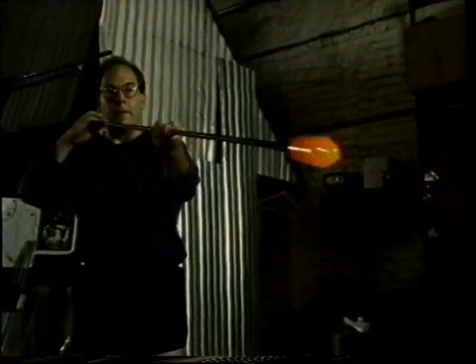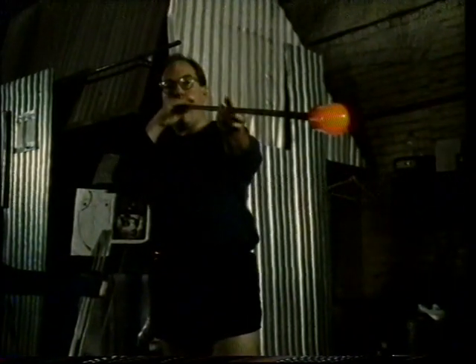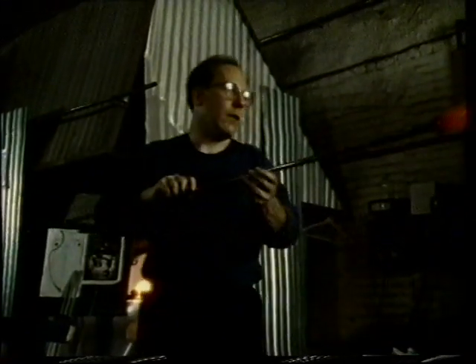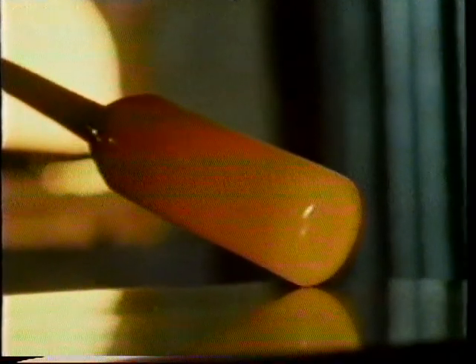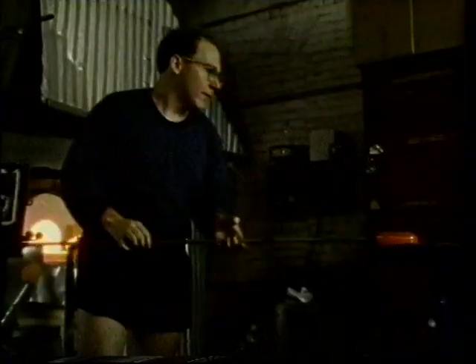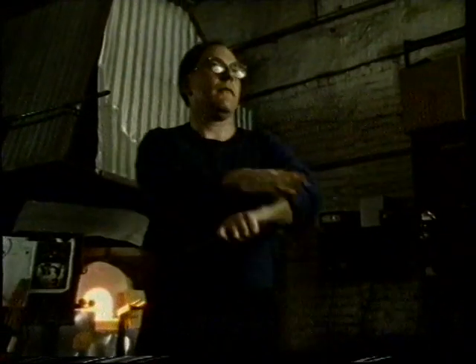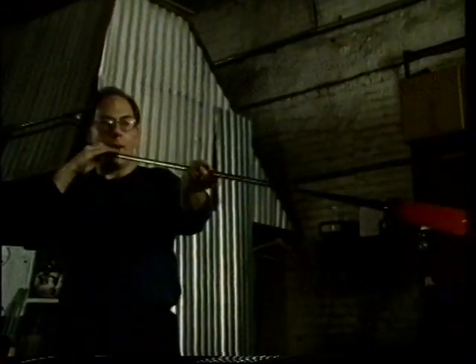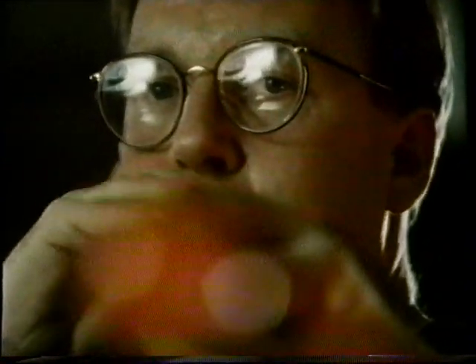I take three gathers: an initial gather to coat the pipe, a second gather, a little bit more glass, and I blow a bubble. And then I coat that with a rather generous amount of glass. The mass on the end of the blowpipe is quite substantial, and I found that to be very awkward. A large mass of soft glass reacts much more strongly to the pull of gravity than a small mass, and you have to work much, much harder, with much greater skill to overcome that effect. We're talking of a very awkward mass of glass which is just dying to hit the floor, drip off the blowpipe.